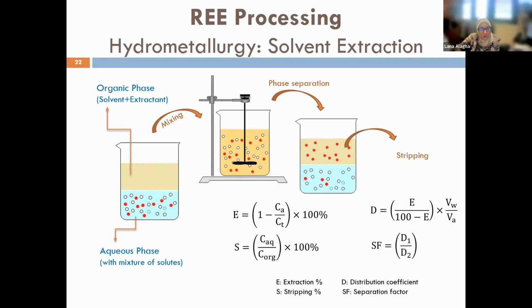Solvent extraction simply is when you mix organic phase with aqueous phase. So it is a kind of liquid-liquid separation. But in the case of solvent extraction application in separation of metals, the organic phase is usually mixed with extractant molecules. So the key of any solvent extraction is the selectivity of the extractant molecules. There are many extractant molecules that have been developed and applied at commercial scale, and some other reagents are novel but not applied at larger scales, and I'll discuss some of these.